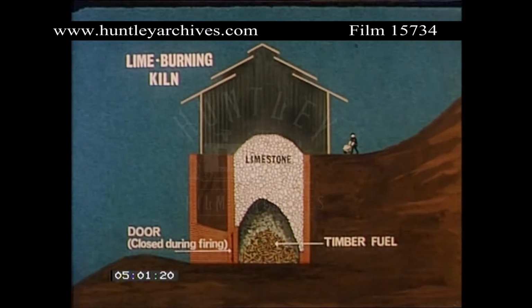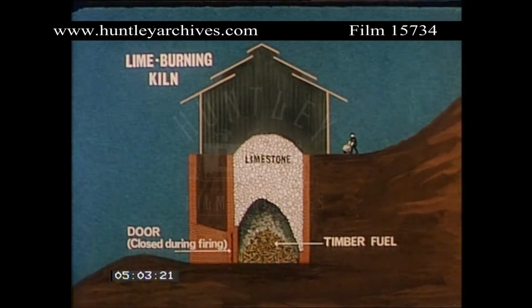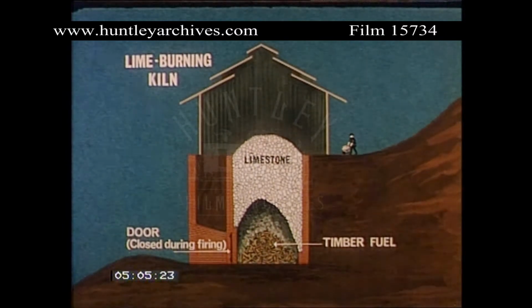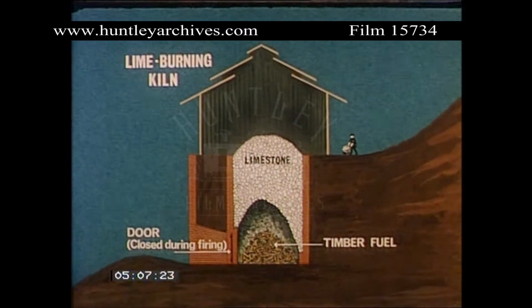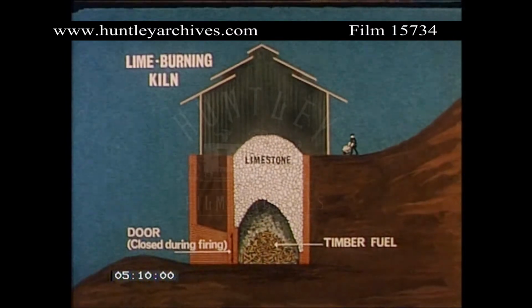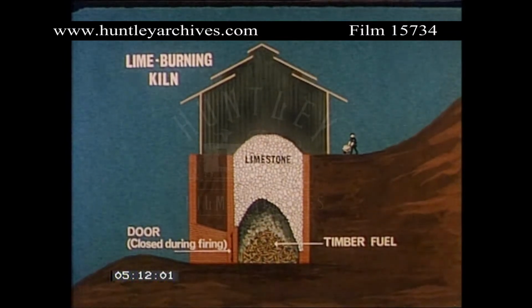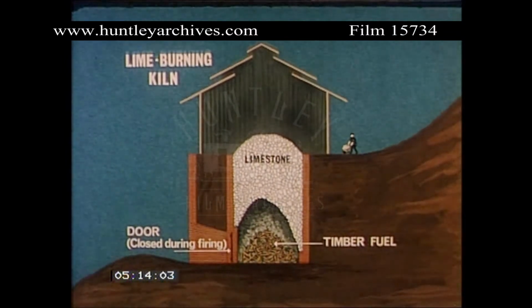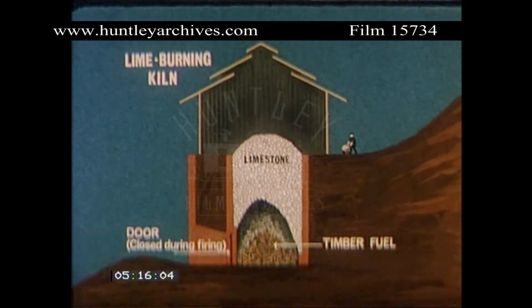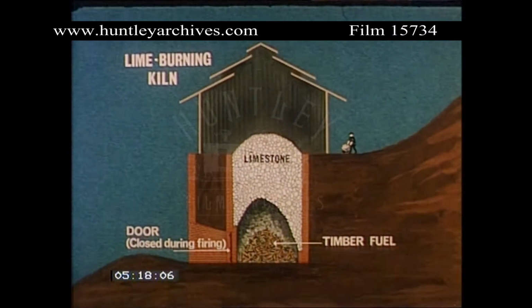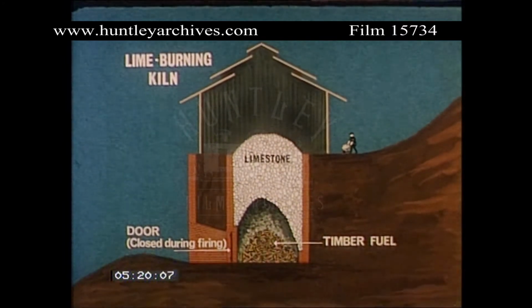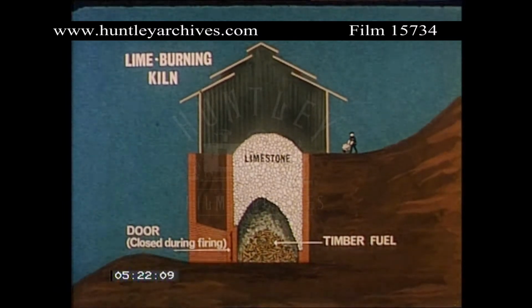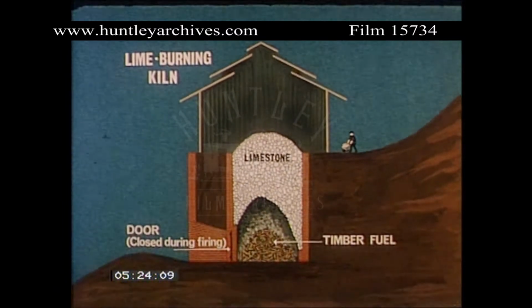A dome is made with limestone blocks at the bottom of the kiln, then more blocks are placed by hand over the dome with smaller pieces towards the top. The hearth is filled with wood to a depth of 4 to 6 feet. It is then partially bricked up, leaving holes for ventilation and refueling. The kiln is fired and stoked for 72 hours. It's then allowed to cool for a further 48 hours with the ventilation holes closed.